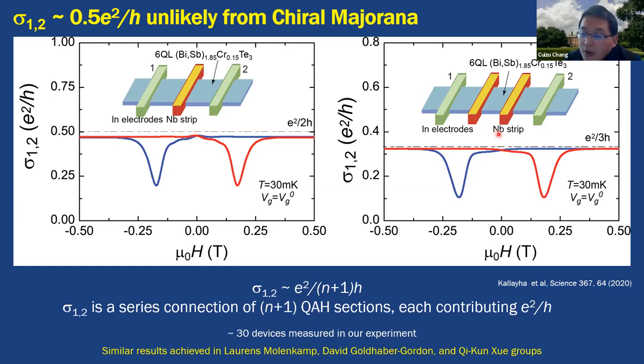You know, we measured more than 30 devices in our experiment, and we always see this phenomenon. So that tells us the e squared over 2h observed in this quantum anomalous Hall and superconductor hybrid device is unlikely induced by the formation of the chiral Majoranas. And a similar result is also observed in Laurens Molenkamp's group, Shoucheng Zhang's group at Stanford, and Cui-Zu Chang's... the Qi-Kun Xue's group at Tsinghua University.